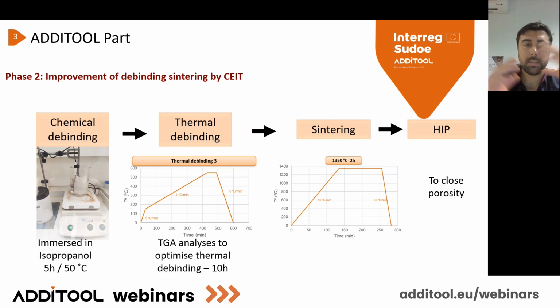And after several trials, they wanted to perform a chemical debinding just before, about 5 hours at 50 degrees, with an immersion of the part in isopropanol alcohol. Okay, it's a classical alcohol that everyone can have in the company. Then they optimized the curve of the thermal debinding, and we see here that we have only 10 hours of debinding and also sintering. And they also perform a HIP to close porosity. We will see just after.